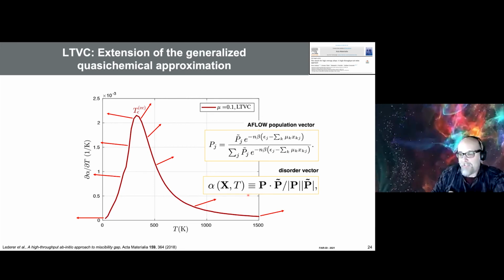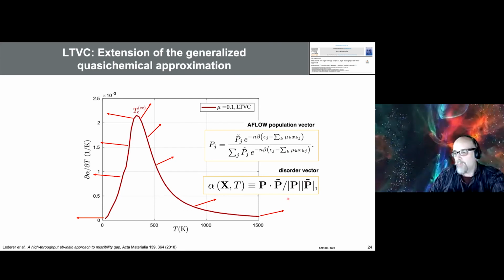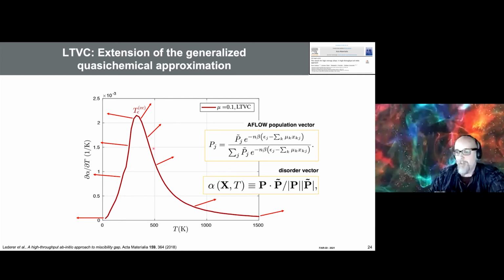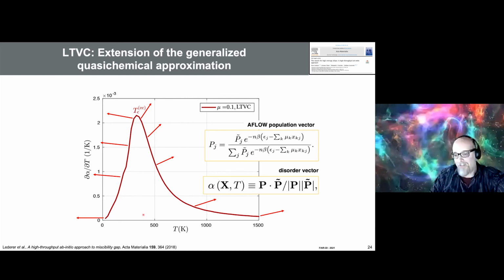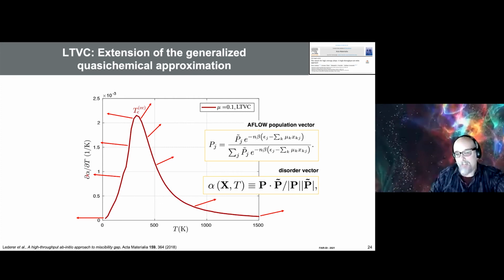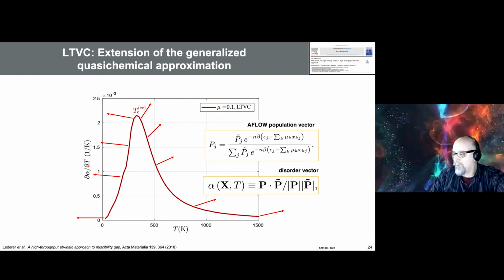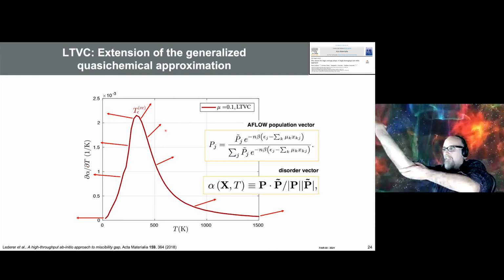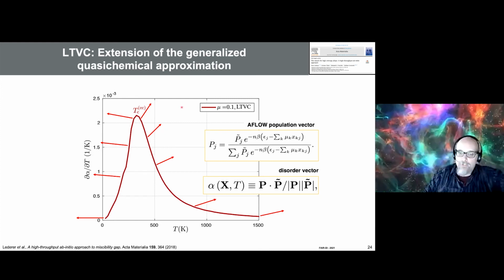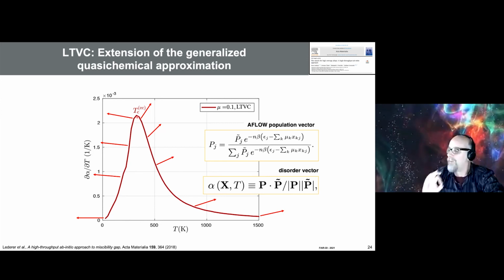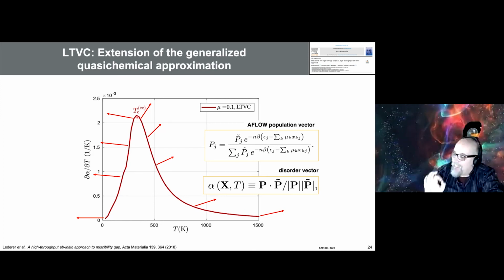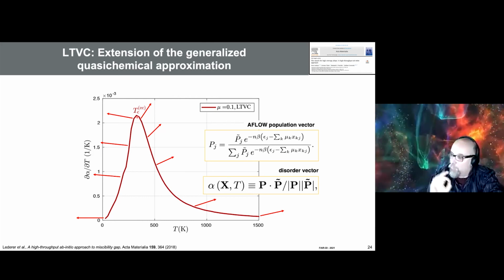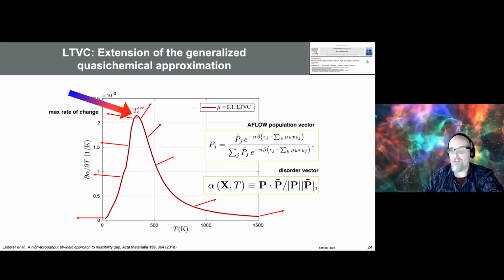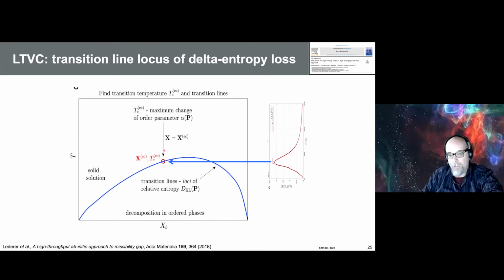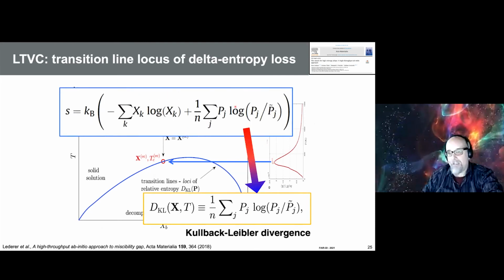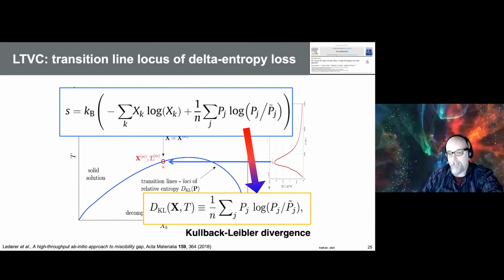And you can calculate how much this vector moves with respect to a reference. We took the infinite temperature because it was much easier, so we don't need to do the phase diagrams. And if you plot the gradient of the angle with respect to the temperature change, you see that it really moves very, very, very slowly. Bam, it jumps. So when it jumps, you have the phase transition. You define the phase transition at the position where you have this big-data-calculated population vector jump, and that's it. You really have the phase transitions. So you go down, you get to this point, and at this point you get the change of entropy, the entropy that is above and the entropy that is below.